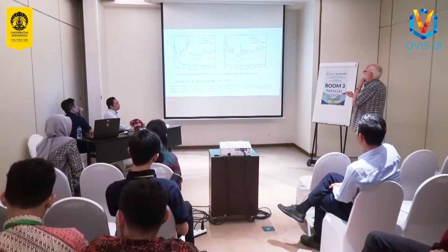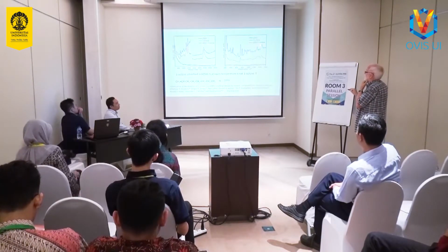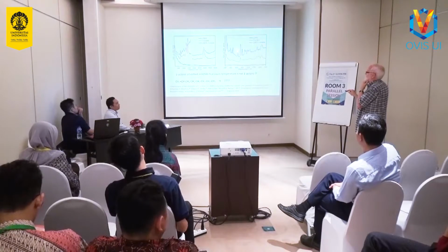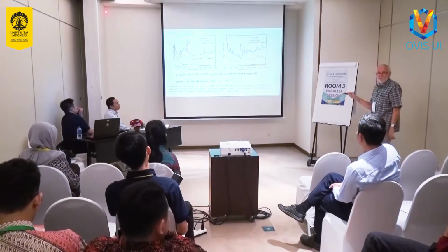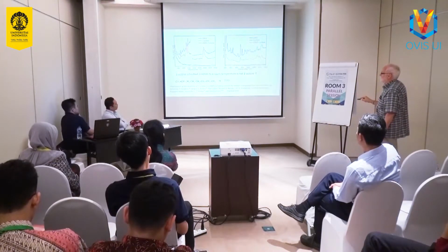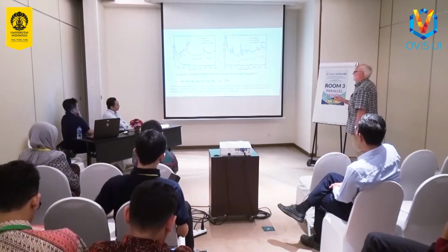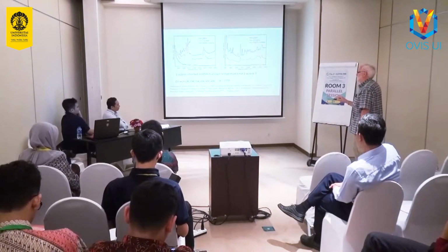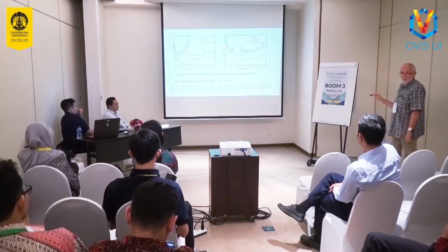But it doesn't look like the spectrum of pure 1-octene. Here's the spectrum of 1-octene by itself, without the zeolite. And you can see we've lost a lot of the vibrational modes. In fact, the modes that we've lost are those associated with the olefinic part of the molecule. We've lost the CH bending and stretching modes associated with the olefin part of the molecule. So it's gone in and it's making something else which isn't 1-octene.